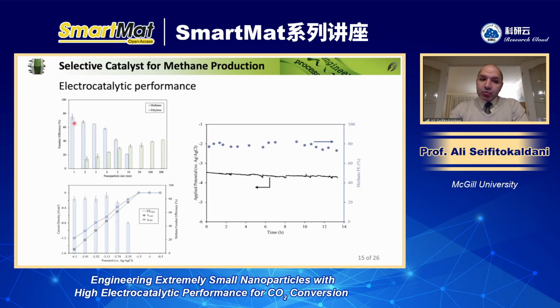And so we are able to produce around 75 to 80% methane with 100 milliampere current density. So we further engineered the electrolyte to achieve higher current density. We also decreased the size even smaller than 1 nanometer. So here you see the results for 0.5 nanometer particles. And the electrolyte is a mix of KOH and also some KCl to just provide enough potassium for the solution.